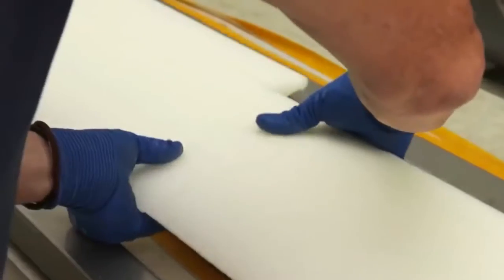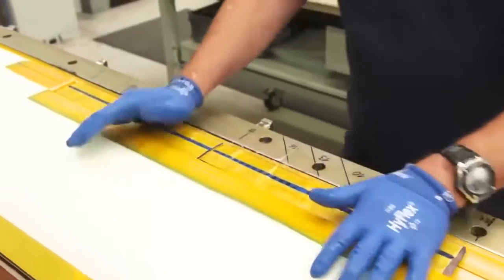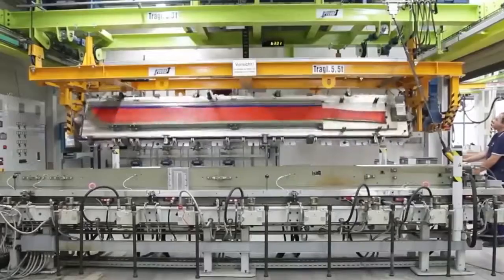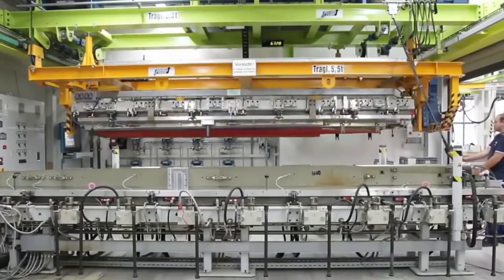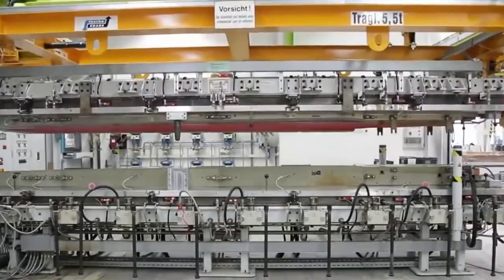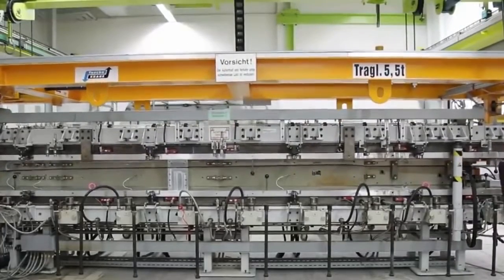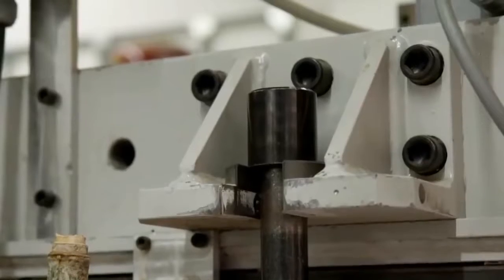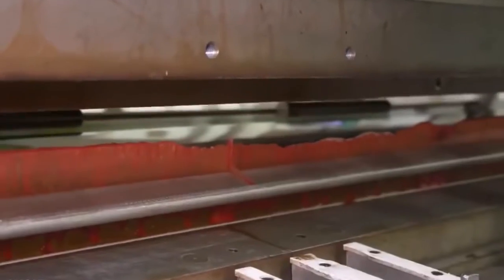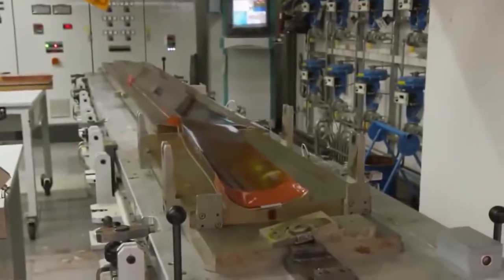The inside of the blade is filled with a light rigid foam core. The half of the rotor blade is put into a special press, the upper half being already in the form. The 2 halves are pressed together with a pressure of 200 bar at 135 degrees Celsius. After 11 hours the process is finished and the carbon rotor blade is ready to go.